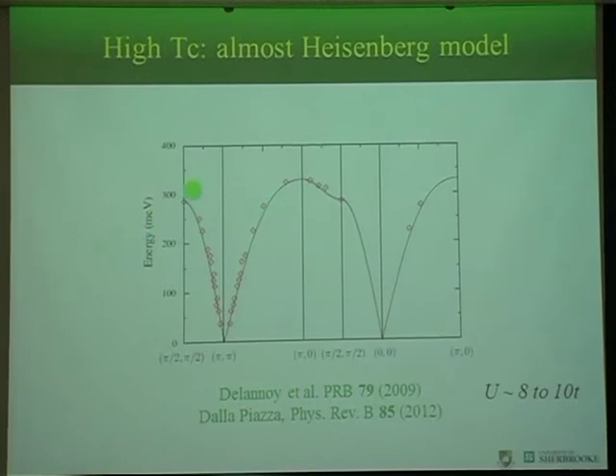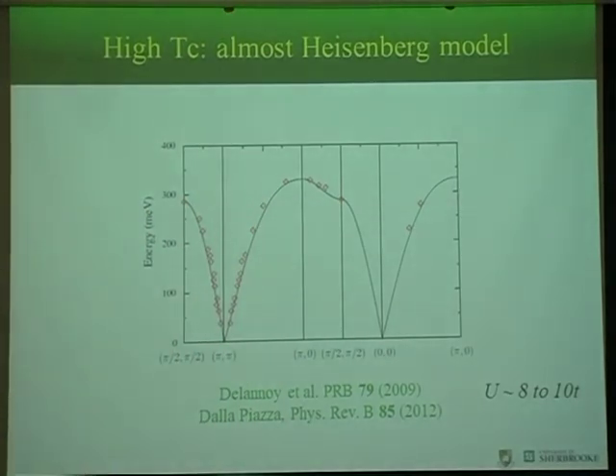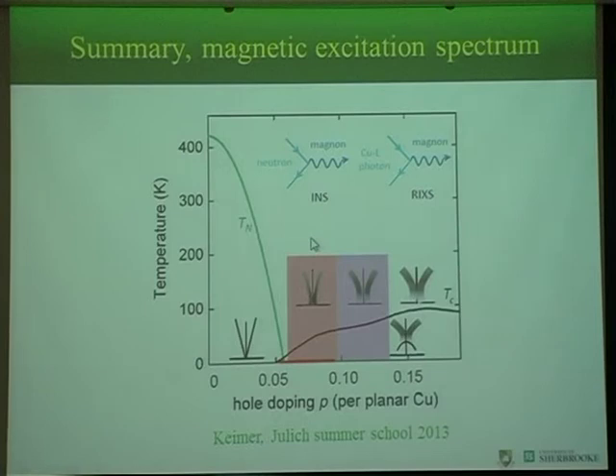Now the spin waves in the high temperature superconductors, this is done on a hole doped cuprate, are given, let's say, by these dots here. That's the experiment. And the line is the calculation. And what you see is that if it was purely a Heisenberg model, here it would be flat. There's a small dispersion. And this small dispersion comes from the fact that you get 4t²/U only if U is very, very large. Otherwise, you get corrections in higher powers of t/U. So you get these so-called ring exchange terms and longer range hopping. And from this, you can find that the value of U for the hole doped cuprates is of order 8 to 10 times hopping.